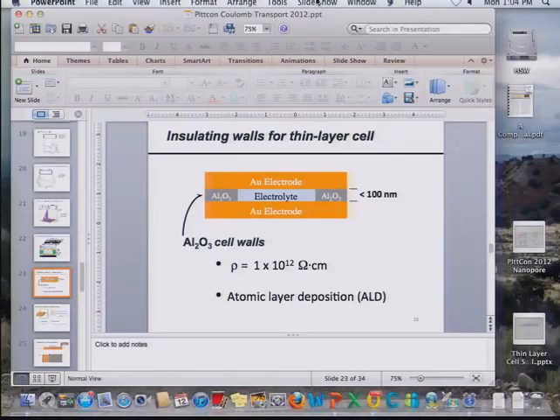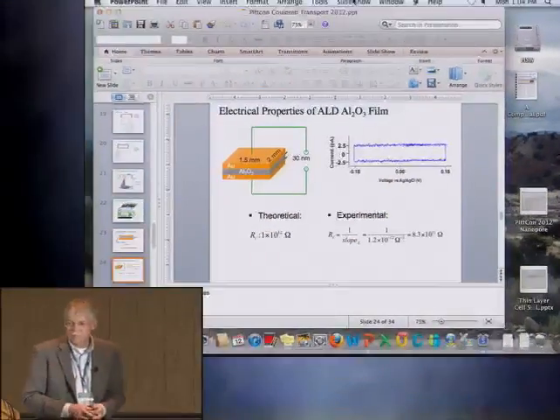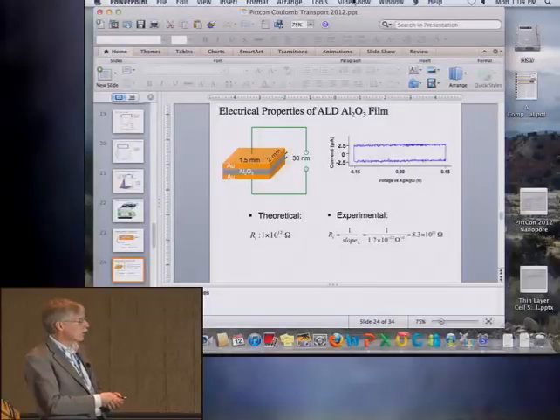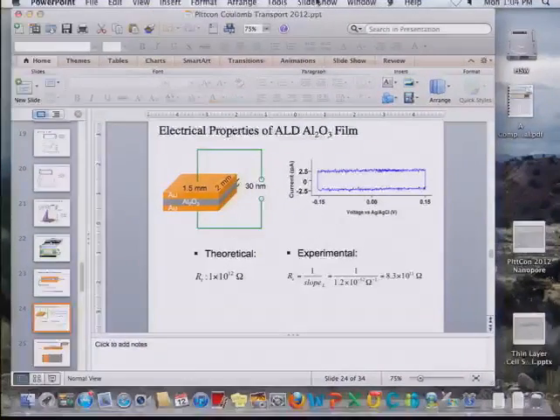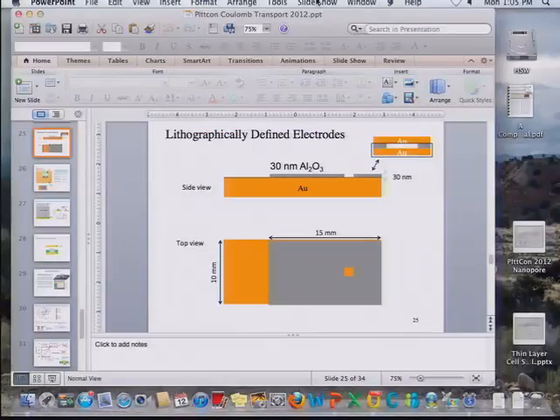It's just standard ALD of the aluminum oxide. We go down to about 15 nanometers, but here's a capacitor of that cell. It's just two gold electrodes separated by aluminum oxide. And for this geometry, 2 by 2 millimeters, you expect a tera-ohm resistance. You measure the current voltage curve, and it's right on tera-ohm resistance. And that's important because you don't want the walls of your cell shorting out the redox chemistry.